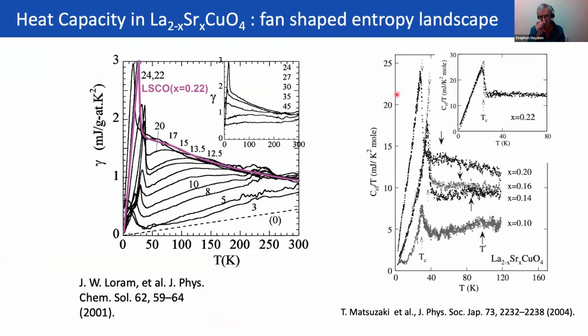Here's something that I guess doesn't get shown quite as much in talks. There's a specific heat of LSCO, pure LSCO. There's two sets of data I've got here. This is some old data from John Loram, 2001. And he has a technique which allows him to go to quite high temperatures by subtracting the background directly during the experiment by doing a differential measurement. And you can see this purple line here is the specific heat for the sample that I'm going to be talking about today, or a sample with the same composition. And you can see it's got an upturn. It's also got quite a high specific heat as you enter the superconducting state here. The specific heat that John Loram quotes his data in is in very strange units per gram atom here. He divides by the number of atoms in the unit cell, as people used to do.